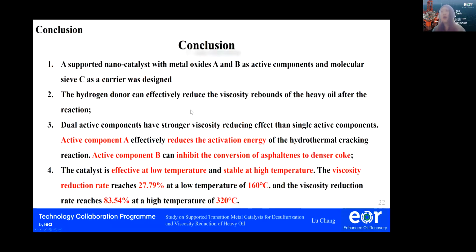Through the research, we can draw the following conclusions. The first is that a supported nanocatalyst with metal oxides A and B as active components and molecular sieve C as a carrier was designed. The second is that the hydrogen donor can effectively reduce the viscosity of heavy oil after the reaction. We also found that the dual active components have a stronger viscosity reducing effect than single active components.